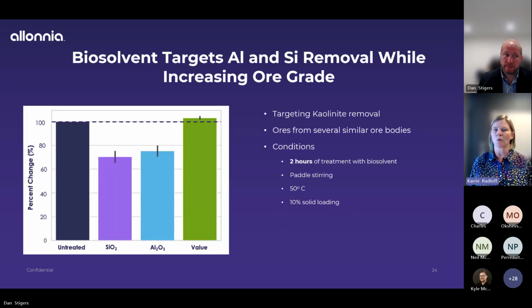So when we've looked at ore materials, this is actually showing results from several different ore bodies that were located in a geographically similar spot. Here we're really targeting the kaolinite removal. We want to get out silica and aluminum. And what we see is that with just 2 hours of treatment with our biosolvent, so that's one of the other things that's really interesting, each of the biosolvents behaves in a different way. So this one was a much faster reaction. It was at a lower temperature, and we were able to remove about 30% of the silica and just over 20% of the alumina that was present in this ore, and that allowed for an increase in ore grade.